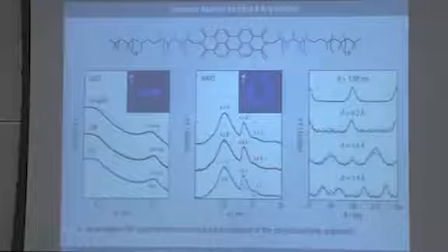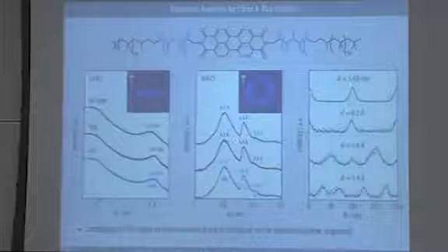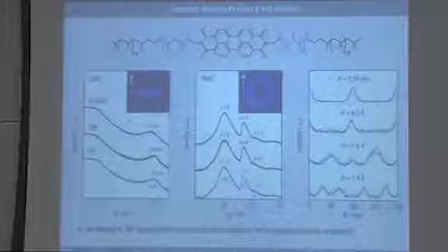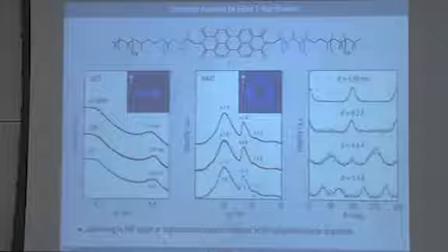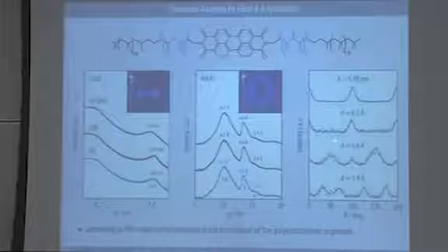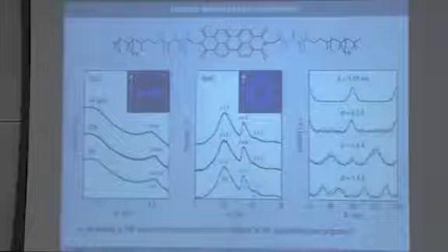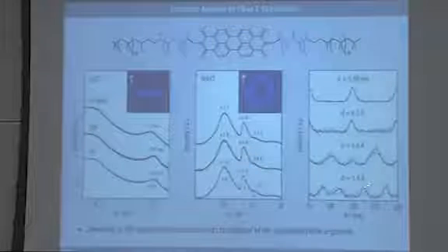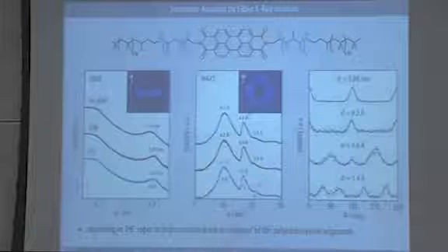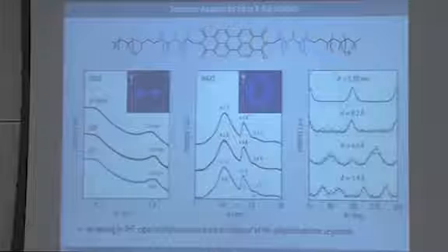Here you see the azimuthal distributions of these 4 peaks. Sure enough, you see that the nanofibrils are aligned parallel to the microfiber direction, as are the polymer chains that are sheared along the shearing direction when we prepare the microfibers. Interestingly, the oligopeptide spacing is oriented at 90 degrees and 270 degrees, again showing that the oligopeptides are oriented perpendicular to the fiber direction. And the pi-pi stacking distance has an azimuthal angle at 48 degrees, consistent with a conical distribution of the parallel quaterthiophenes, with an angle relative to the fiber axis of around 48 degrees.